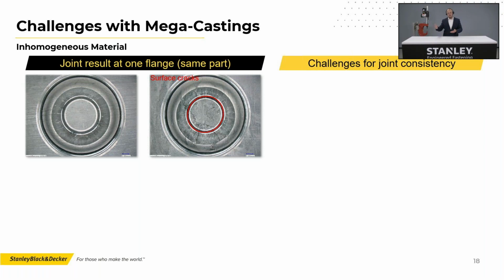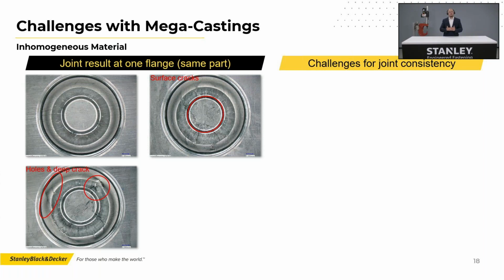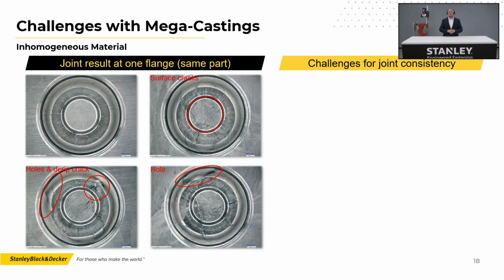So you do another one close to the second one, 2 centimeters on the side, and you see again something else. You see, oh, there's a hole now, and there is a deep crack. When I say deep crack, I talk about cracks that go really deep. If you do the cross section, they go really deep up to the rivet itself. So basically the material is completely broken at one side. And you do the fourth one, and then you can see, oh, there is the hole again, which was not there in the first and the second one, but on the third one. So you have many different outcomes on the same part, because this material is inhomogeneous, right?